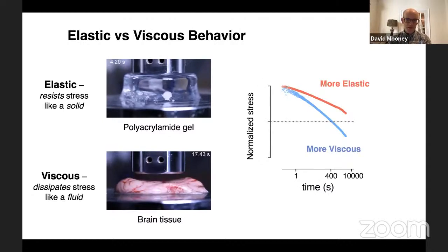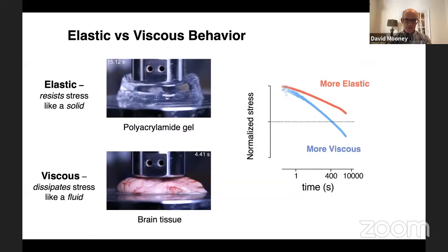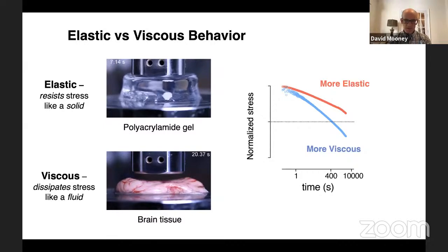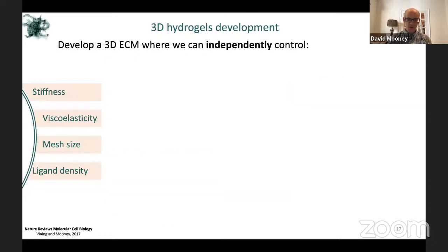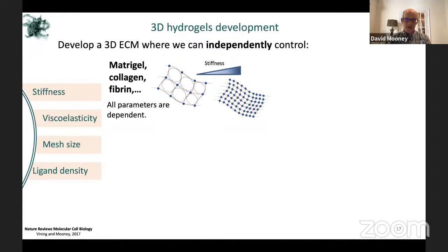Now, throughout the rest of the talk today, materials are not typically purely elastic or purely viscoelastic. So I will tend to talk about materials that are being either more elastic or more viscous, or elastic versus viscous. And one way that we oftentimes look at this is by looking at the rate at which they dissipate the energy, and the more viscous materials will dissipate the energy more rapidly, as shown in the curves here to your right. Okay, so we want to examine now a number of variables and understand their impact on cell behavior. And we need to actually have a system where we can independently vary each of these. The stiffness, the viscoelasticity, we want to independently vary the mesh size, and the ligand density and type for cell adhesion. Now, this will lead us to actually re-examine for a minute why we use these alginate gels.